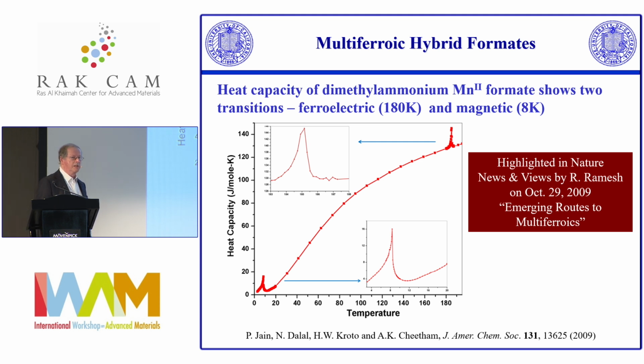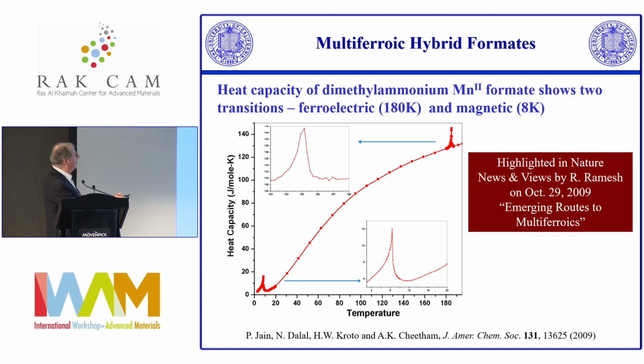And I realized that maybe since these things will order magnetically and they're ferroelectric, they should be multiferroics. And we published a paper in JACS on this in 2009, and Ramesh from Berkeley published the News and Views in Nature on it, Emerging Routes to Multiferroics. And I was delighted until I saw that his News and Views article was getting more citations than my original work in JACS. And happily, that only lasted about a year. And then people, you know, this is now a very highly cited paper. But it was the first example of a multiferroic that's actually driven by hydrogen bond ordering, which is what we're dealing with here in the order-disorder transition, rather than an off-center displacement of a metal cation.